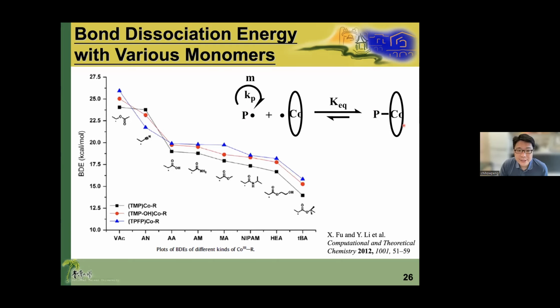So you can see vinyl acetate radical has higher energy, so that in vinyl acetate radical polymerization, all the cobalt-2 was converted to organocobalt-3. However, with methyl acrylate, you can see its radical is more stable. So once the radical becomes more stable, the equilibrium goes back to the left-hand side. So in methyl acrylate polymerization, the cobalt-2 and organocobalt-3 coexist and reach the equilibrium. That's why when we use a different monomer, we need a different catalyst.